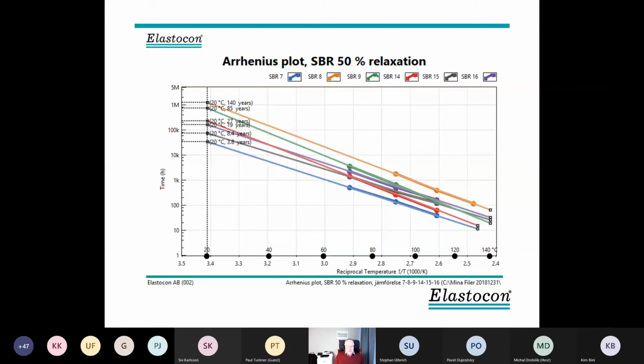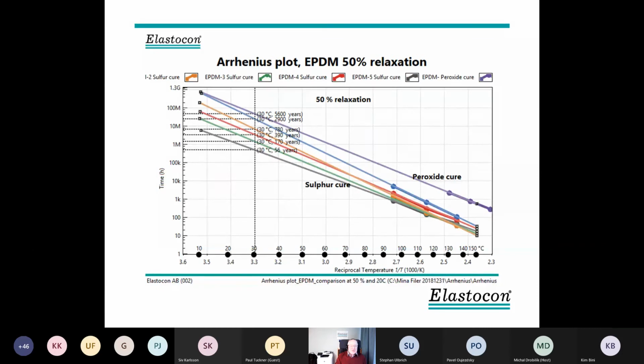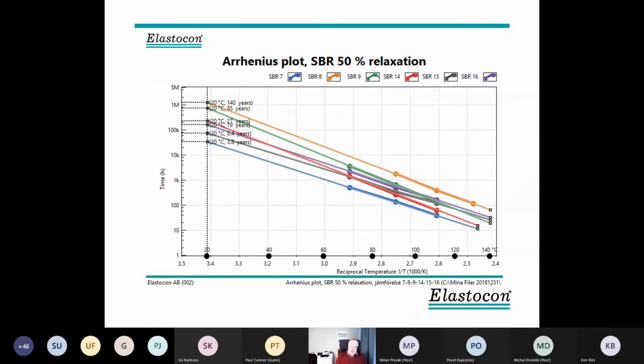We also tested SBR, also from the present production, and we saw on sale in the market. There we see quite a big difference from about 3.8 years up to 140 years. But please note that we have gone down to 50% relaxation. We believe that the sealing ring in a water pipe with quite low pressure difference will function to much higher relaxation figures. But this gives a good comparison between the materials. We can still make a quite good SBR material, which is, I think, as good. This was 30 Celsius. A good SBR can be almost in the same range as a poor EPDM.